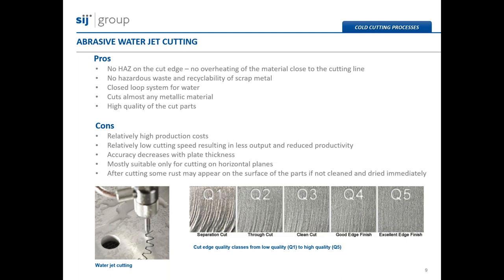Abrasive water jet cutting is a cold cutting process where a high-speed water jet with a dispersion of small but very abrasive sand particles cuts through the plate. The main advantage of this process is that we do not have any heat affected zone on the cut part, and therefore it is highly recommended for high carbon equivalent value grades. During abrasive water jet cutting, there is also no overheating of the material near the cutting line, and therefore we have no microstructural and mechanical changes in the cutting region, so just pure base metal.